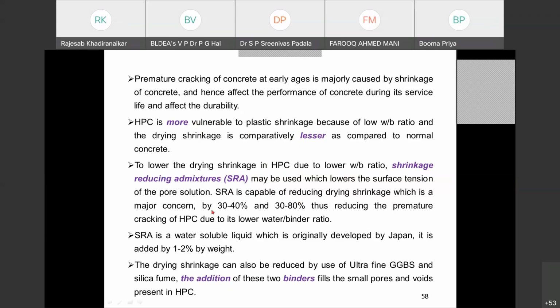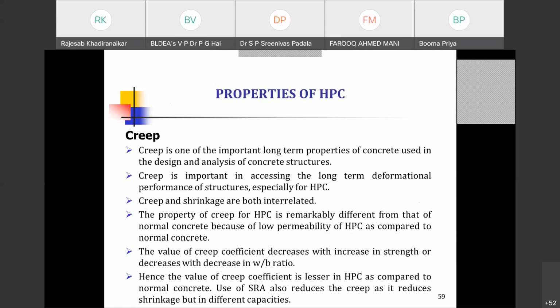That's a major concern, around 30 to 40%. And 30 to 80% reducing the premature cracking by the HPC. So these shrinkage reducing admixtures, they are water soluble and developed in Japan. So it's added by 1 to 2%. Drying shrinkage can also be reduced by use of ultra-fine GGBS-based particles, silica fumes. Then the other binders, you can reduce that.